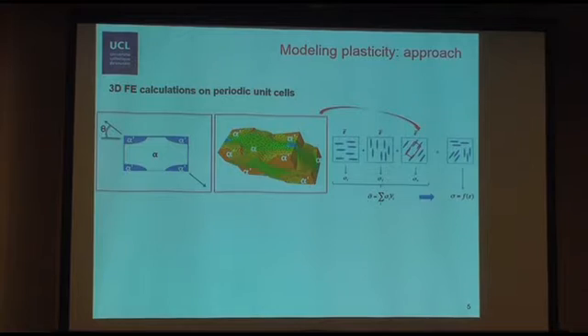For the modeling of it, we used 3D finite element calculations on periodic unit cells. Finite elements were chosen because we wanted to have the effect on the local fields due to the presence of an inclusion of a particular shape in a particular direction. And the axis of the local fields is also important for the modeling of damage, as I explain very briefly a bit later. Each unit cell is a ferrite matrix containing an inclusion of martensite. And what changes from cell to cell is the orientation of loading, the loading being always tensile.